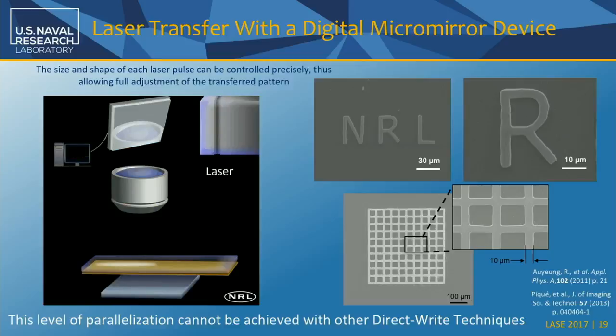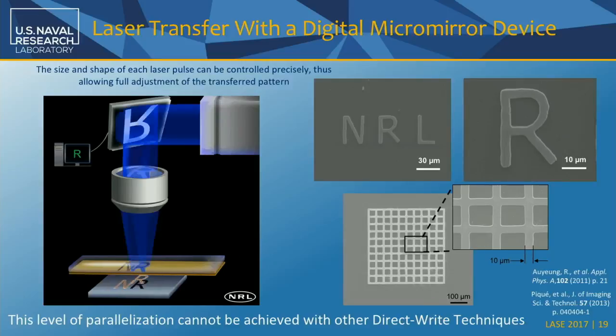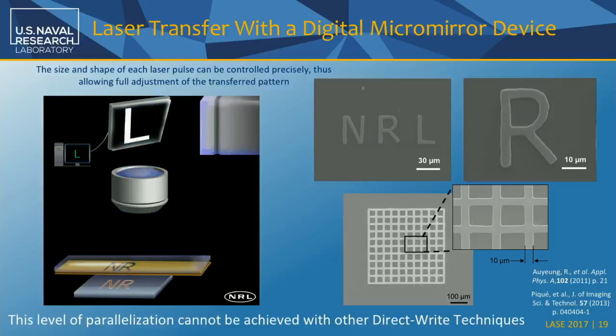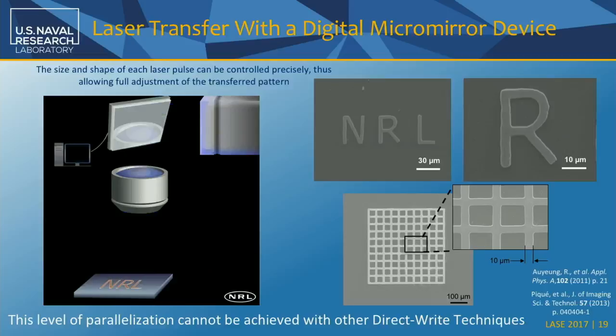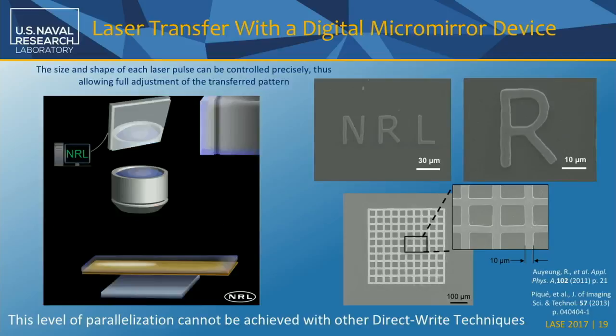And here's the actual product of that. This was done on silicon again. It's nice and flat, so we can get good images. And you can see now that entire character, and this could have been a pattern for an electronic interconnect, can be printed in a single laser pulse.